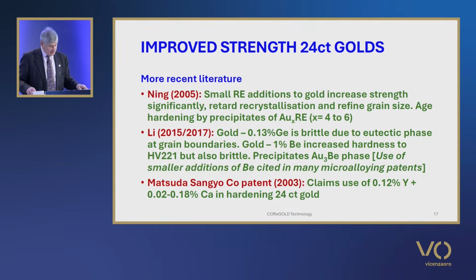We look at more recent literature on microalloyed 24-karat golds. Further research has been published since my review in 2005. The effect on properties of rare earth additions such as cerium and gadolinium to pure gold and gold alloys has been reported by Ning. He showed that small additions to both pure gold and gold alloys increase the strength significantly and retard recovery and recrystallization, as well as refining the grain size.